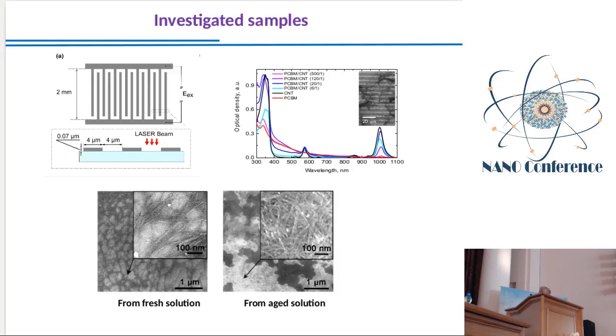Okay, so in fact, carbon nanotubes are not very technological materials. It's relatively difficult to prepare samples. For example, usually these devices are based on thin film devices where our active material is placed between two plate electrodes, but in that case it's quite difficult to prepare samples because shortcuts take place and it's difficult to prevent this. Therefore, we used a slightly different technique for our investigations.